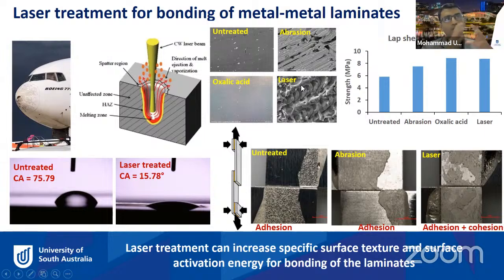For example, you want to bond it together with another one, and as you can see, the laser treated surface becomes very rough. So this rough surface is quite beneficial for bonding strength. That means when you have the adhesives in between the two sheets, the adhesives can flow into these rough cavities and then make a very good bonding between the sheets.